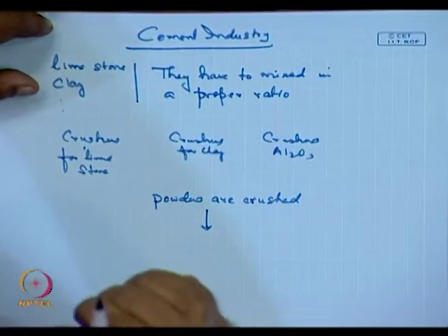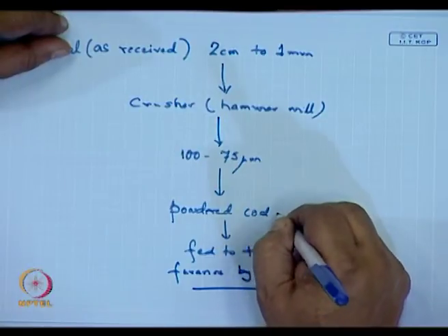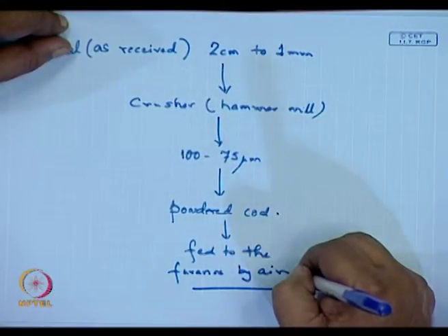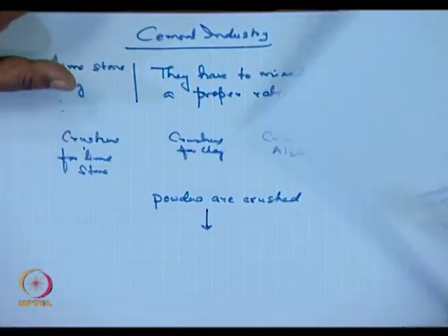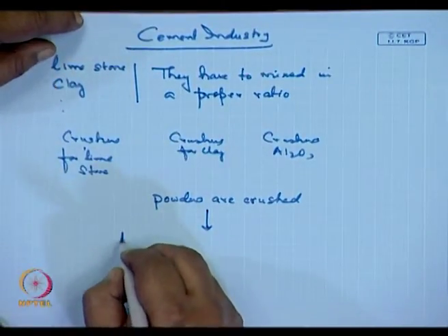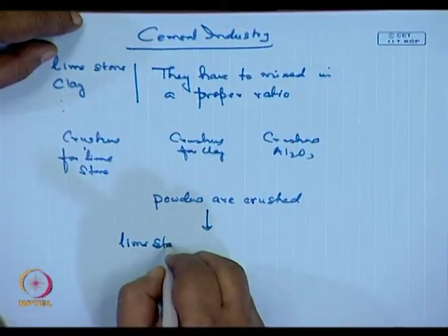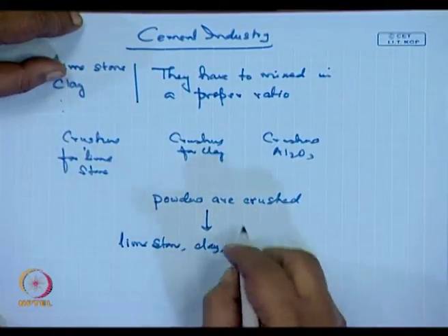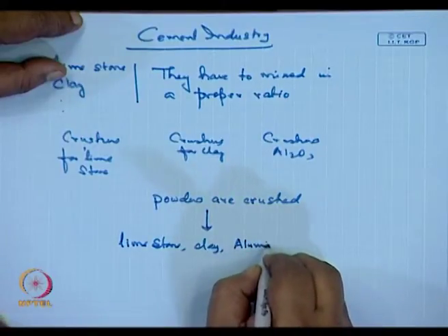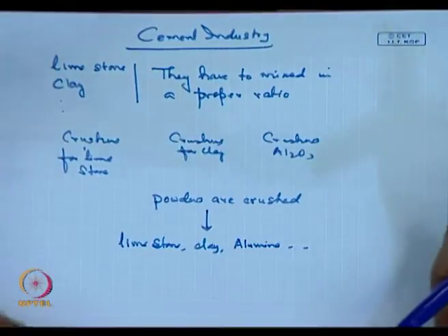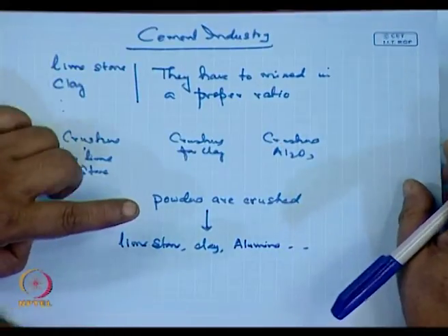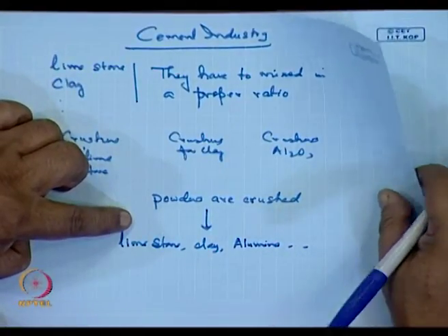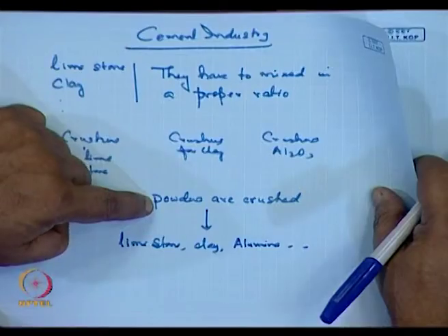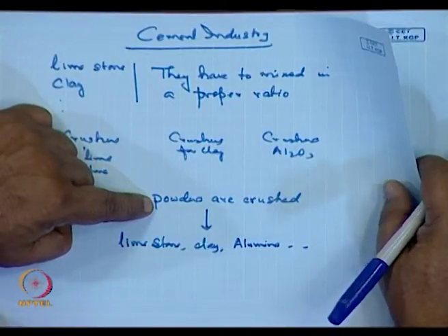Here is a fundamental thing. While in the coal, what is happening? This powdered coal is being fed to the furnace where it burns up. But in cement industry, the limestone, the clay, the alumina, and any other additives have to be mixed in a proper ratio. So here in cement industry, one more factor comes in. These crushed powders are directly not fed in for calcining.